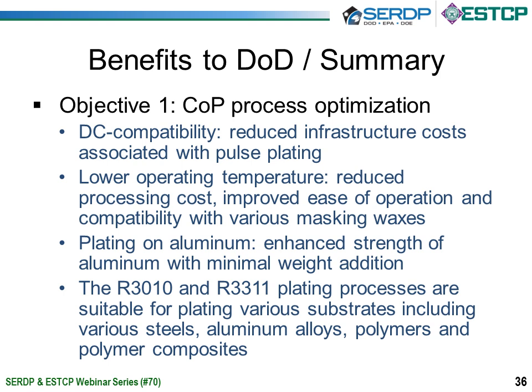So a quick summary of what we've achieved to date in the project as it relates to benefits to the DoD. So objective number one, the process optimization, results in the DC capability or compatibility, which will result in reduced infrastructure costs when trying to deploy this new technology to conventional plating shops. Pulse plating works very well, and it gives you lots of flexibility. But when looking to put this in a new plant, that results in extra infrastructure cost. So it's great that we can get the process to work with conventional direct current plating, which is the typical type of rectifier you see in plating shops. The lower operating temperature now should reduce processing costs and improve the ease of operation and compatibility with various masking waxes. So that is a good advancement.